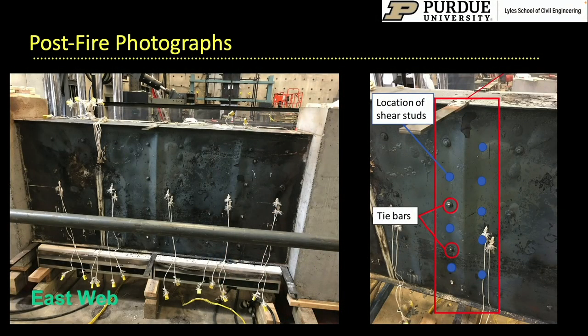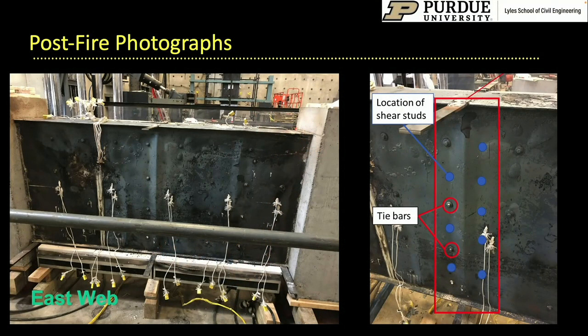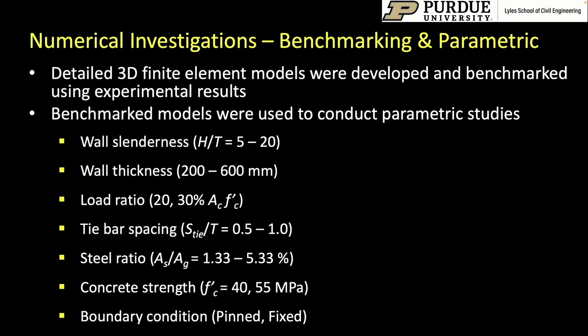So we found that that concrete provides a very strong heat sink for the system, to the point where, in spite of all the load that had been applied to it, the specimens never failed, and had fire ratings in excess of 2 hours for the 1/3 scale 9-inch thick specimens. Here are some photographs of the specimens. You can see the local buckling that has occurred in between the tie bars in the steel plates. That's a close-up of that, locations of shear studs and tie bars and the local buckling in between.